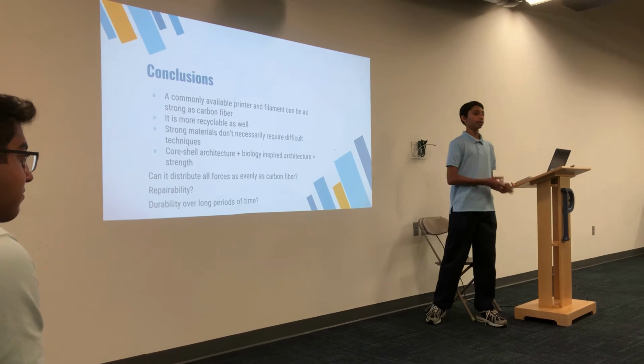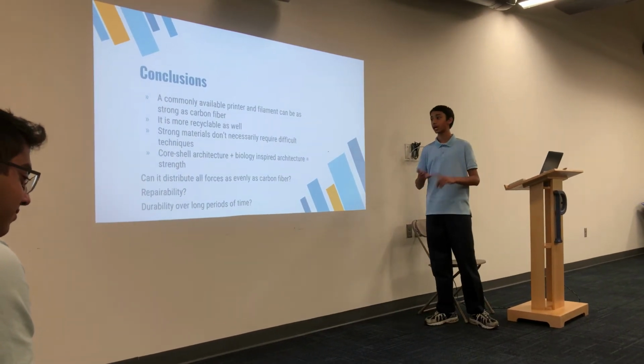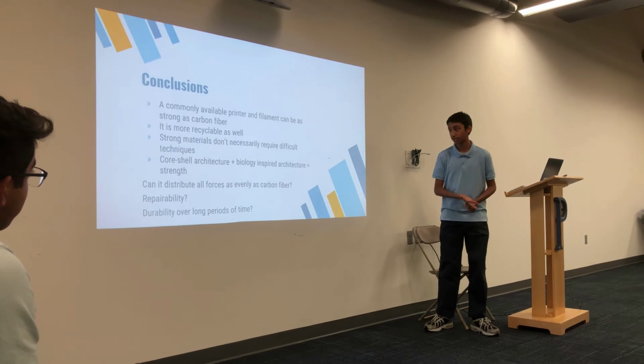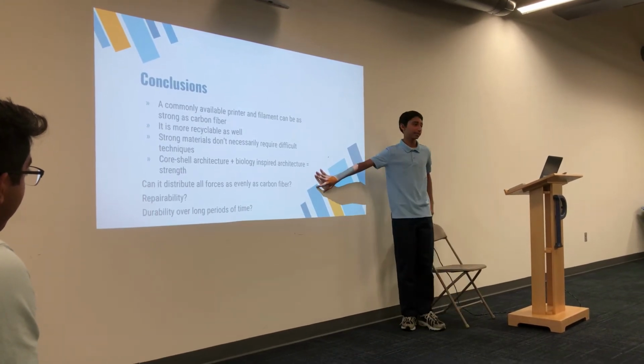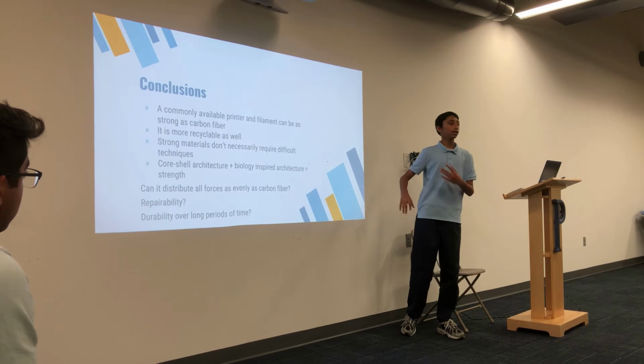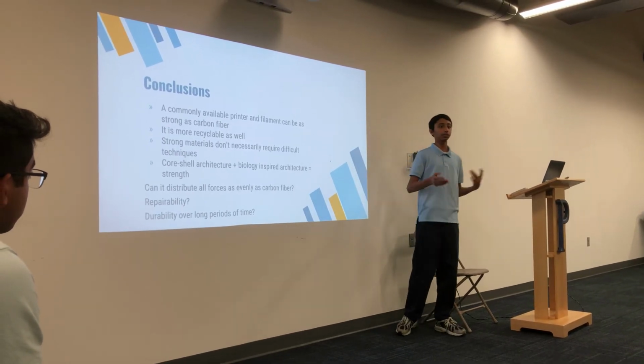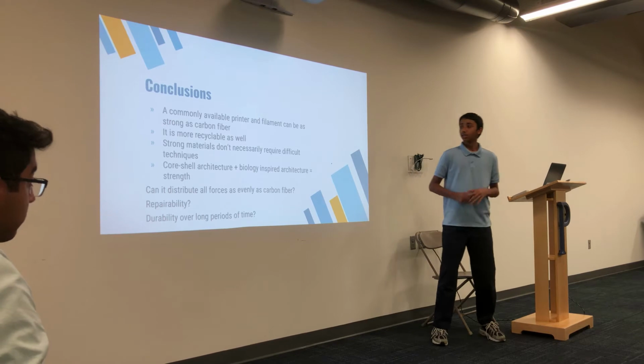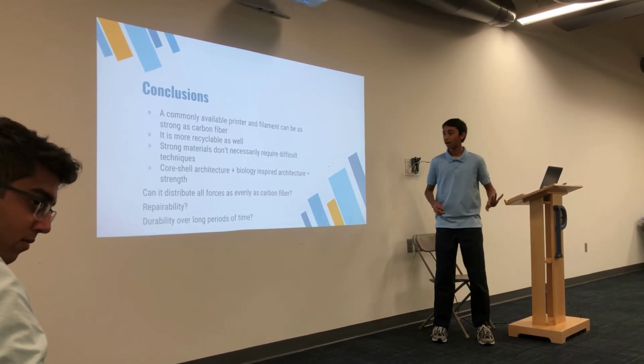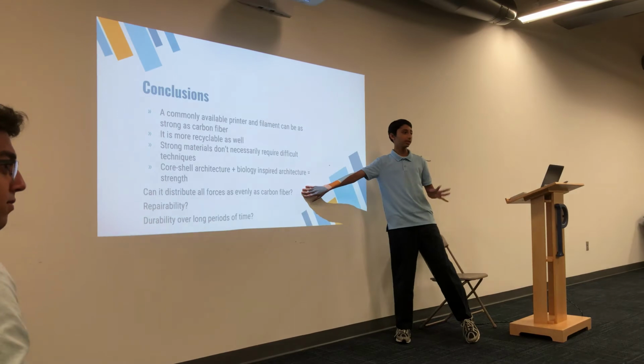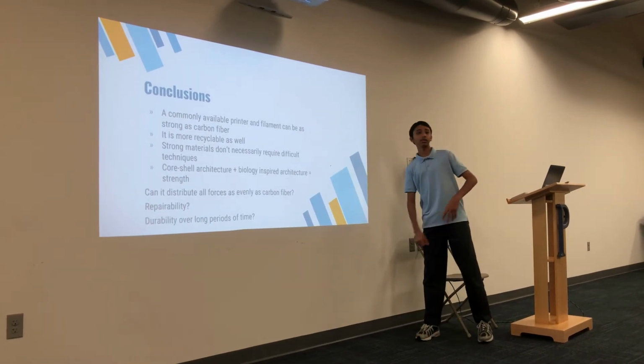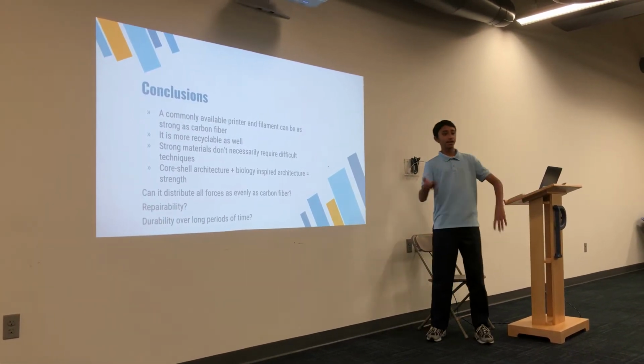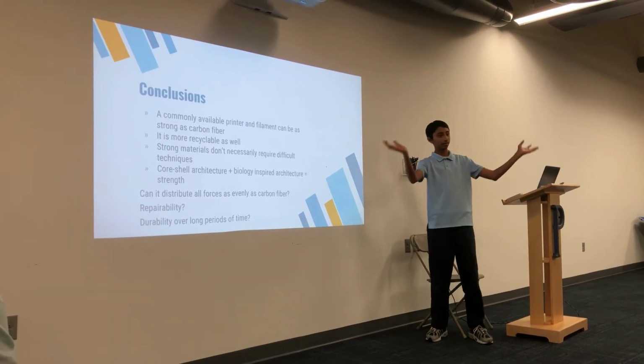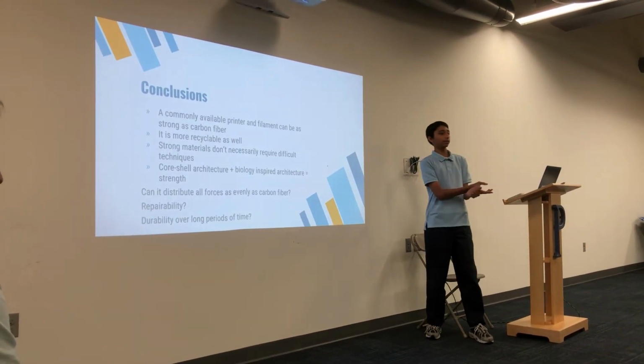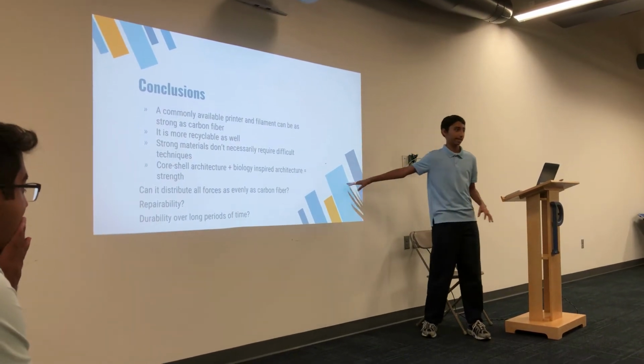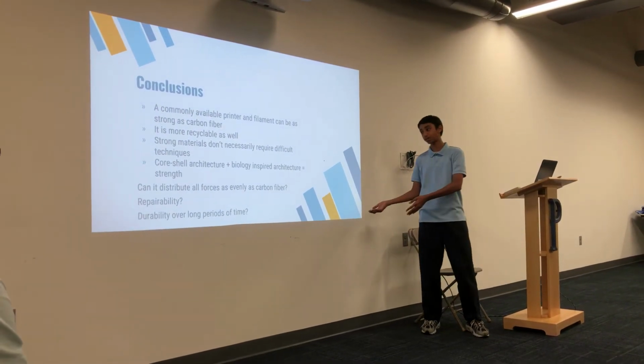And what this shows is that you don't necessarily need these really difficult, high energy, high intensity techniques to make such a strong material. And going back to basics, that biologically inspired structure is going to be really helpful, as well as the material which is forming that core shell architecture. Some of the questions that they didn't really answer: they don't really give a lot of comparisons to carbon fiber. There are 2 figures in which they compare it, and in addition to carbon fiber, there's like 30 other materials included in the figure. So it's very difficult to conclude, from all these tests that they did, how directly the material compares to the carbon fiber.